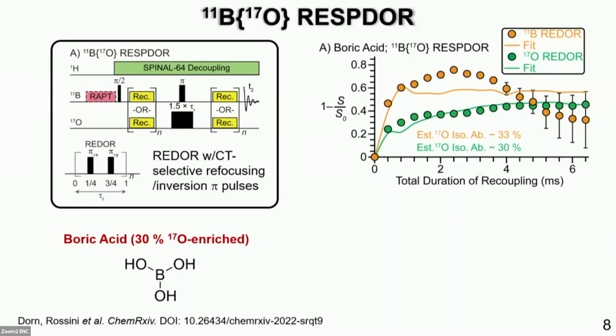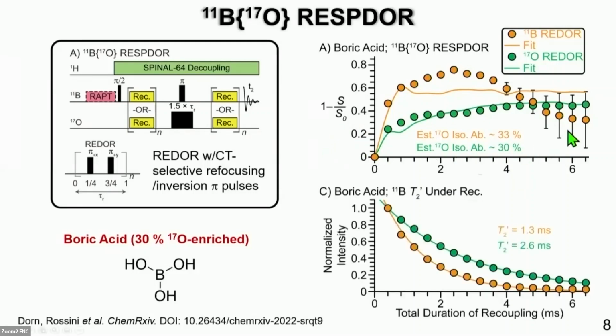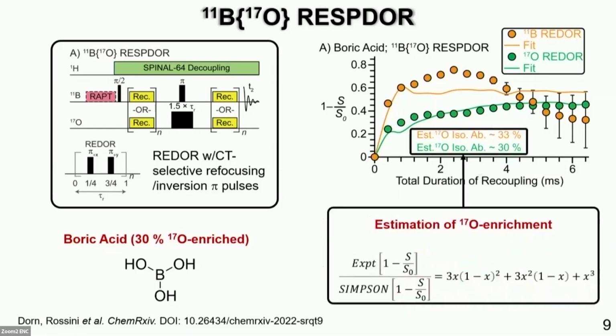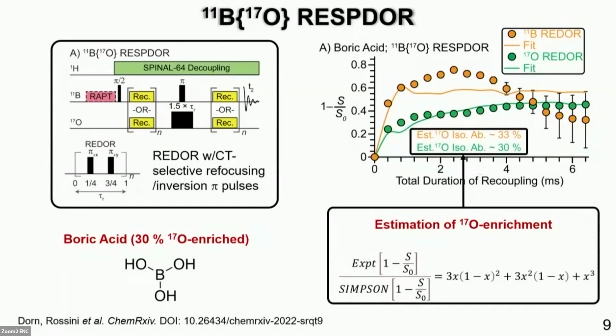You'll also see that there's a lot more error at the end of these curves for boron recoupling, and that is because the T2 is also significantly shorter when you apply recoupling to the observed spin, which is not too surprising. Nevertheless, we can numerically simulate these experimental curves, and by scaling the extent of dephasing to match what we observe experimentally, we can estimate the oxygen enrichment level. And this is because the overall extent of dephasing is going to be dependent on how many oxygen atoms are attached to boron with the 17O isotope. And what you can see is that we get very good agreement with that determined from solution NMR spectroscopy.